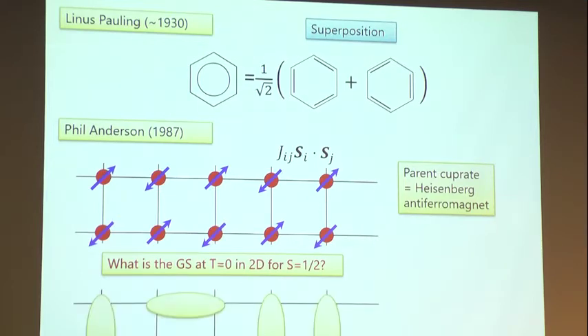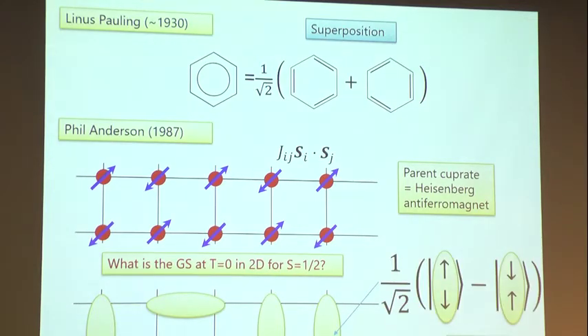So Phil Anderson proposed that maybe it's not a Néel state at all. It is something like this. And this is a kind of bad graphical representation of a resonating valence bond state. What it is: you take 2 spins, and they can form a so-called spin singlet or spin triplet. A spin singlet state is non-magnetic, and it has the lower energy when you have antiferromagnetic interaction. So you can imagine that there's a spin singlet on these two sites and two sites here and so on. This is one way of imagining the ground state of spin singlets, often called a valence bond state.